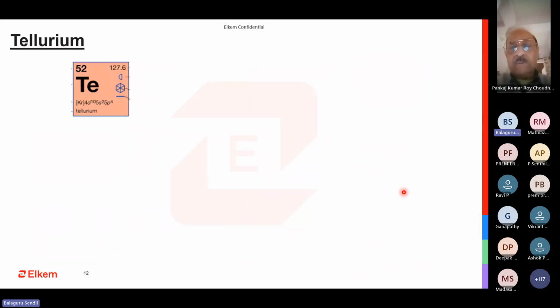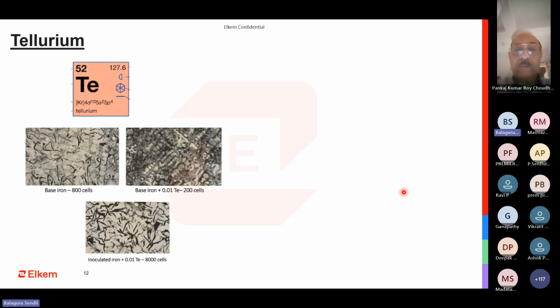The next is tellurium. Again, tellurium is also not so bad when it comes to its impact. The base iron in this case at 800, base iron plus 0.01% of tellurium completely killed it. It made sure that there are no flakes. Everything was more into D and E type graphite, which is not required, which will have different mechanical properties and is not very useful for engineering applications.